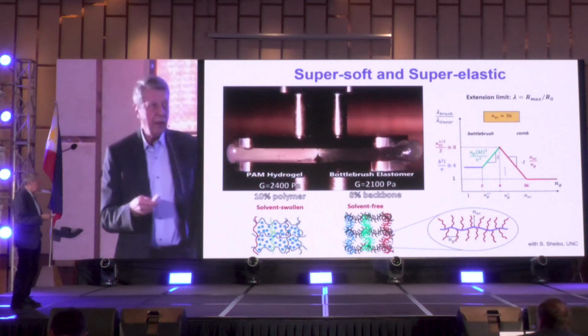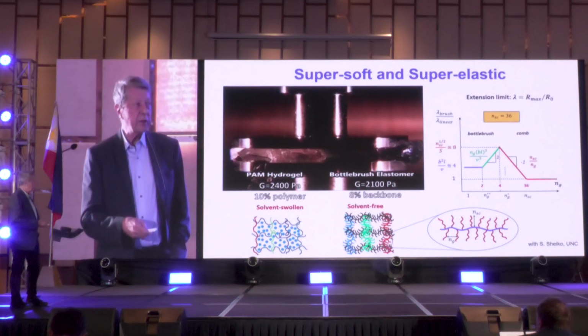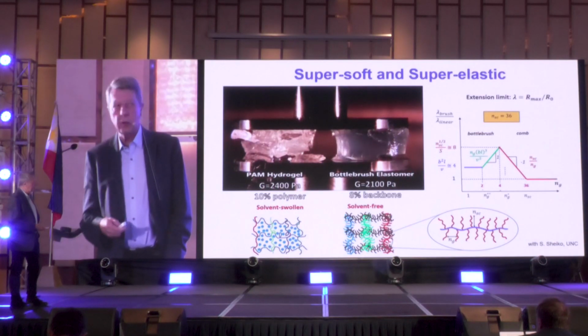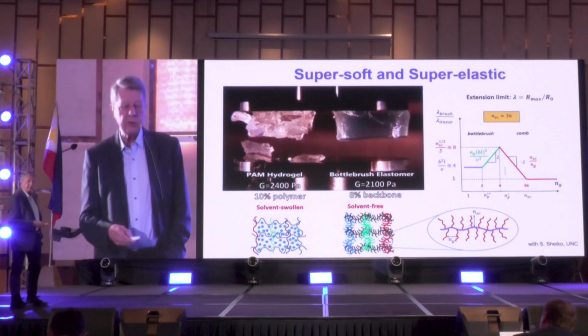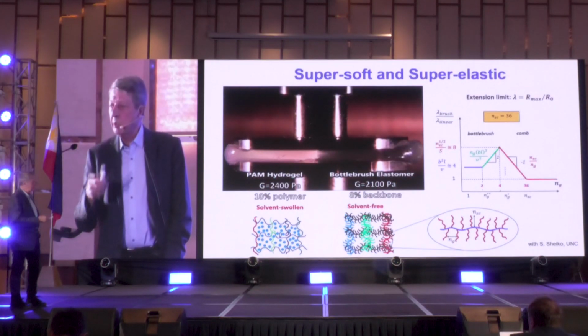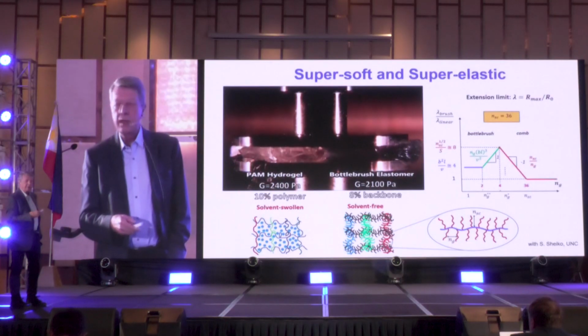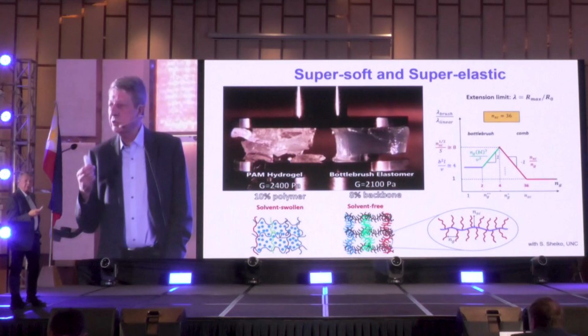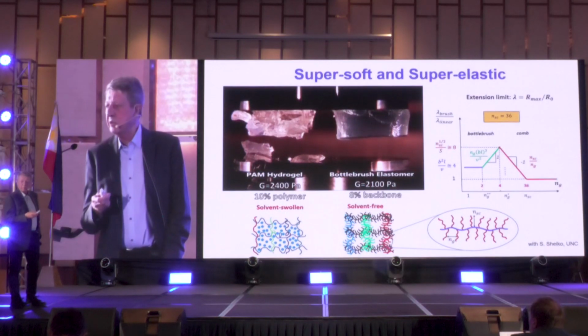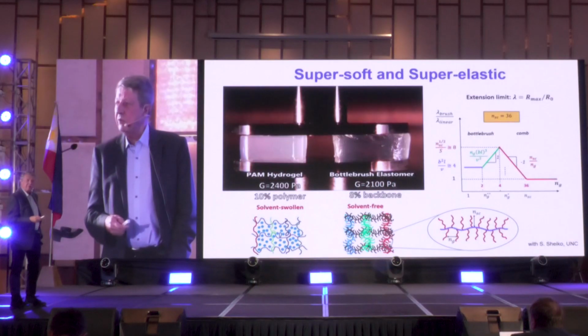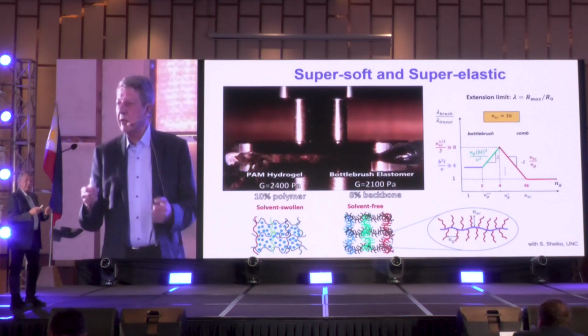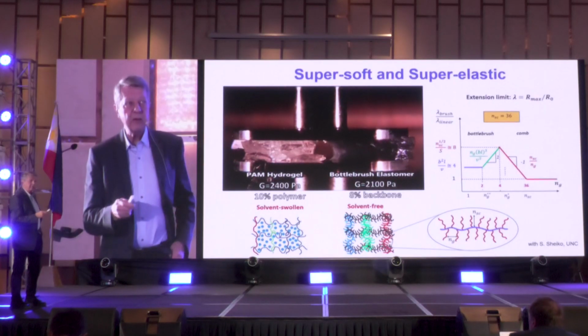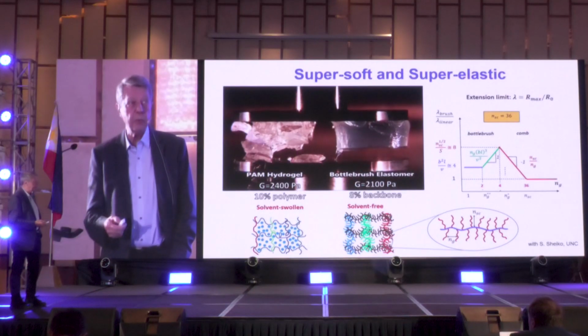Yes. So you could see here what happens if I take a hydrogel, this is 10% polymer, 90% water. This is polymer backbone, 8%, 90% side chains. So when you press them, you could see that this reversibly can recover all properties and is this super soft material, and this hydrogel is much more brittle. So you need to design these materials properly, because it's not only the length of a side chain, but also the distance between these side chains. If you have too short a distance, sometimes they become really brittle as well. So you can design them by using these two, or you will see later by three properties.